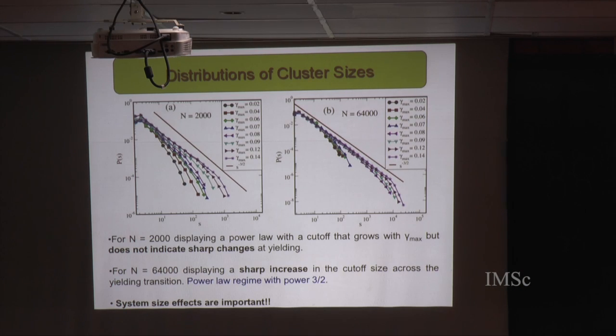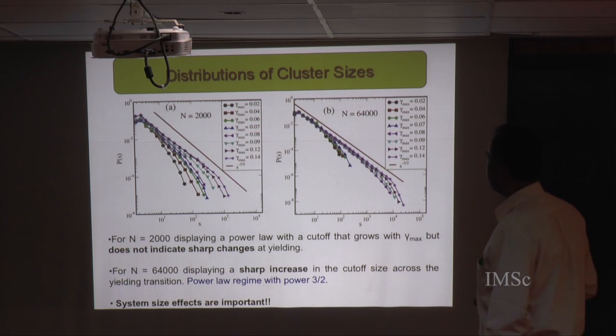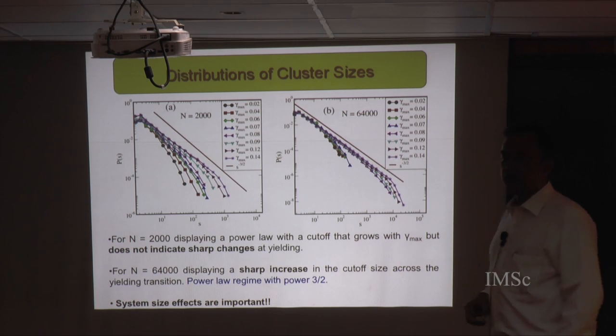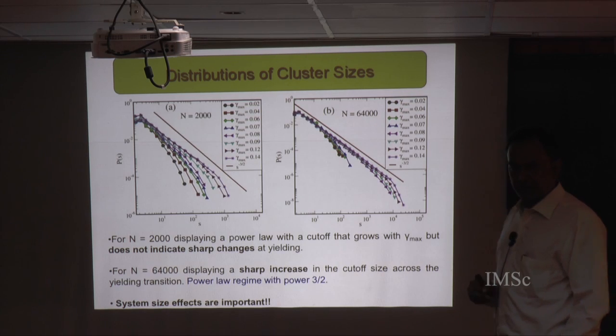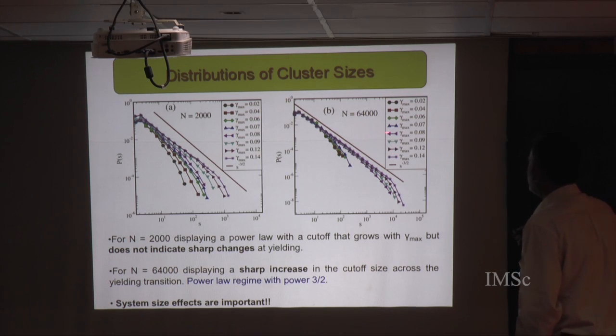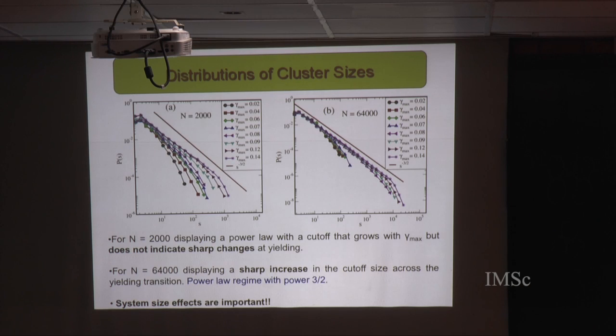Okay, so then we sort of realized, after staring at data like this for a while, that we should really be looking at different system sizes and understanding the size effects. So here is a much larger system, and when you look at the same data for this larger system, you begin to see that indeed there is a difference between the 4 small amplitudes that are all clustered out here and the larger amplitudes which begin to now show a fairly clear power law regime.